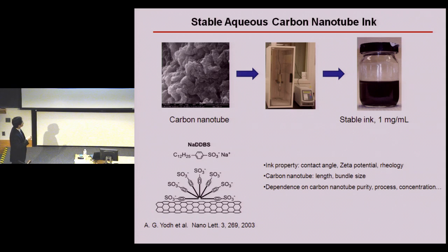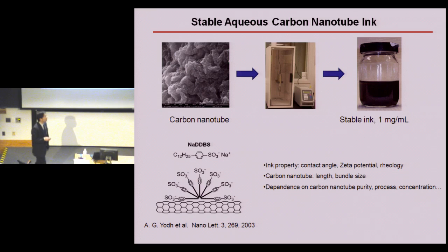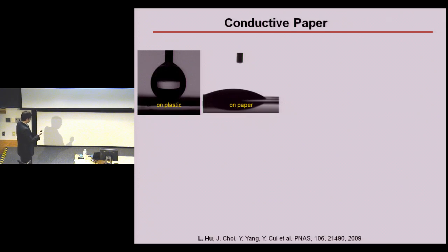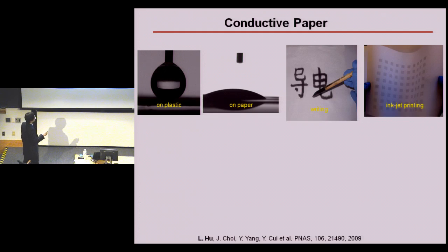With the help of mechanical force, we can disperse nanotubes into water and get this stable carbon nanotube ink, with the concentration typically 1 milligram per milliliter. After that, we can coat carbon nanotube ink onto different substrates. You can see here on plastic, you have a high contact angle. On paper, there is very good wetting, which is not surprising to us. And we can write this conductive ink onto paper, or we can do inkjet printing.